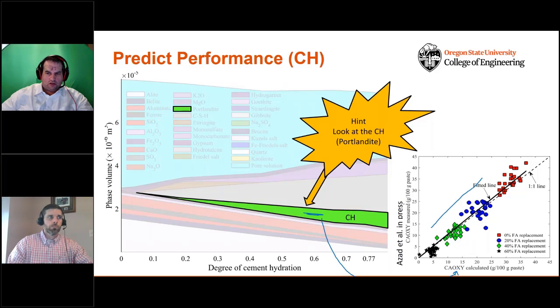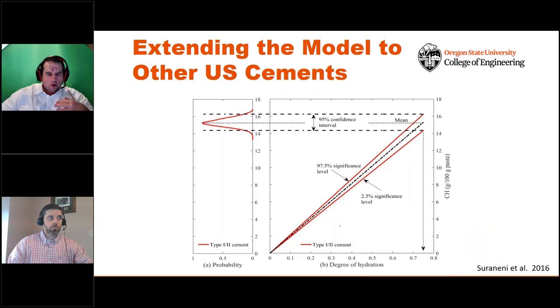You see there's a very good correlation to what we see when we do these same experiments in the laboratory. We then started to work with some of our friends at PCA, and they were able to provide us with information on the chemical distribution of all the cements in the US, and we combined that with the distribution of all the fly ashes that are being used to make concrete. We performed an analysis called Monte Carlo simulation. Rather than making 2 mixes or 3 mixes, we can computationally make, I believe, about 350,000 different mixtures. By making those 350,000 different mixtures, we were able to provide a 95% confidence band on the amount of calcium hydroxide being produced as a function of the degree of hydration of the system.